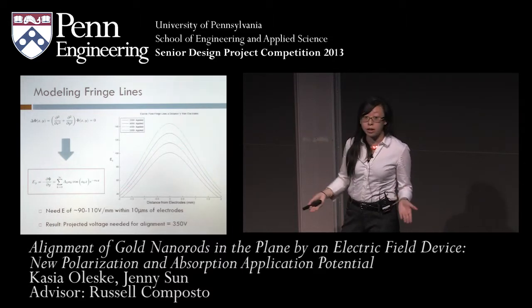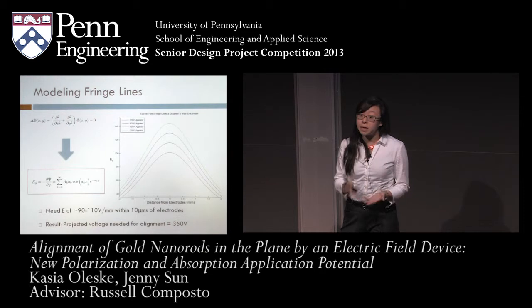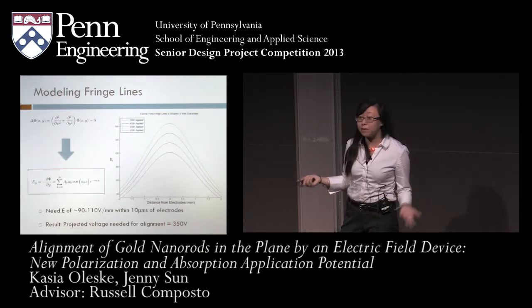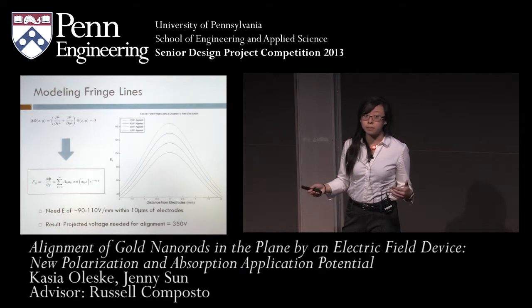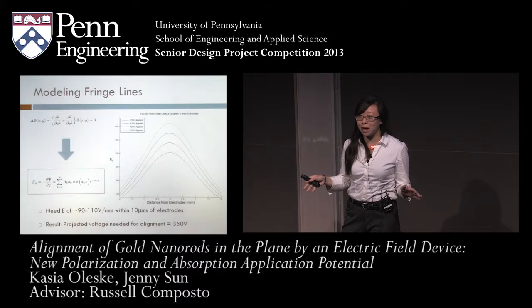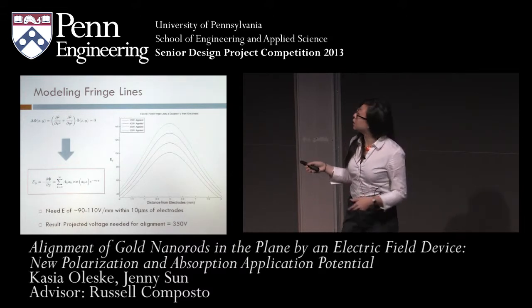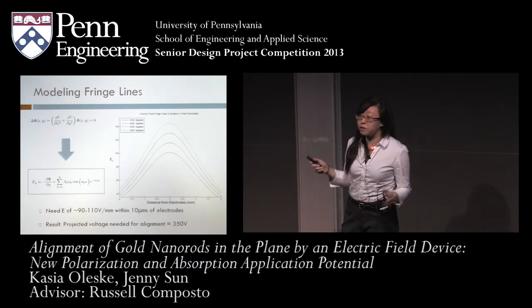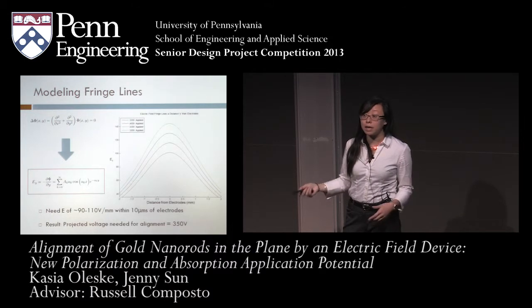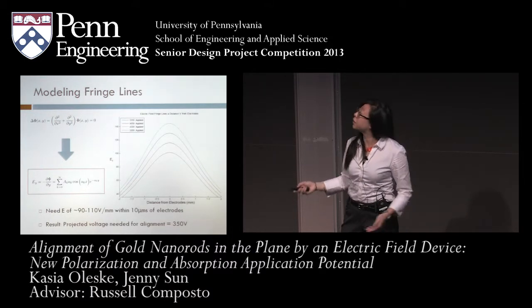And so we knew from literature, from people who had done the alignment perpendicularly in the past, that we needed an electric field strength of about 90 to 110 volts per millimeter. And so based on our distance of about 10 microns away from our electrodes, we knew we needed about 350 volts through our electrodes in order to actually achieve that electric field.